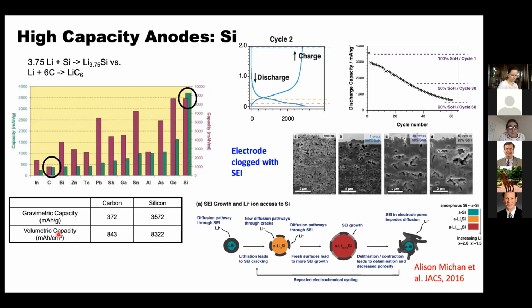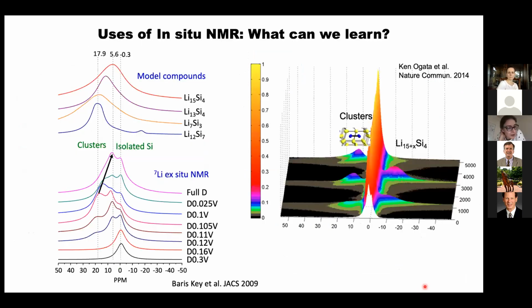So what we did was to look at this a number of years ago, but I want to illustrate what the problem of this material is, that it's so reactive when you form these lithium silicides. It reacts with the electrolyte to form this passivating layer called the SEI, or the solid electrolyte interface, and you gradually lose energy density. And so this is work in 2016 that we did, but what we did first, almost 7 years previously, was to really understand what was going on in terms of the structure.